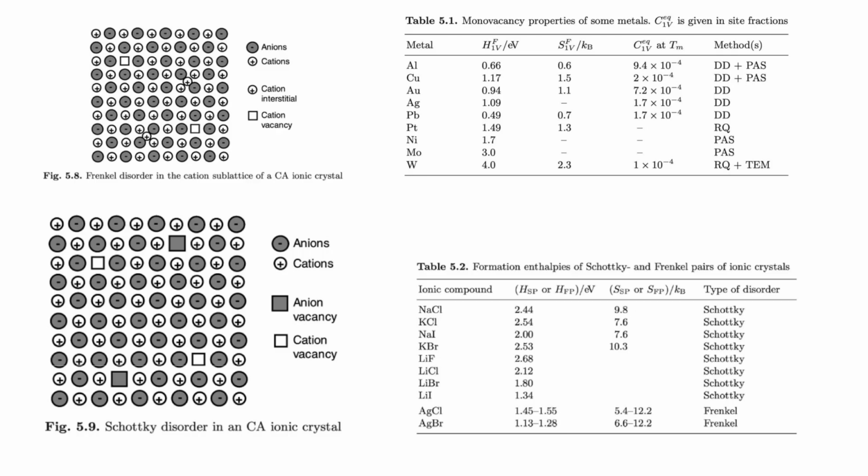But if we just do that, we have a problem, because when you take one positive ion out, it's not charge balanced anymore. So the system's not going to be happy if you simply remove one positive ion. So we need to also remove negative charge, so we remove an anion, a negative ion, from here. So we can keep it neutral.